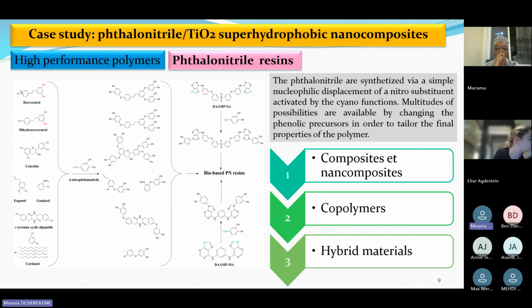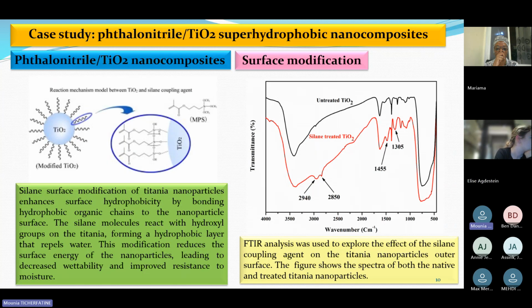Prior to the nanocomposites preparation, a chemical surface modification is applied to the titania nanoparticles to improve their adhesion and dispersion within the polymer. The silane surface modification of titania nanoparticles also enhances surface hydrophobicity by bonding hydrophobic organic chains to the nanoparticle surface. The silane molecules react with hydroxyl groups on the titania, forming a hydrophobic layer that repels water. This modification reduces the surface energy of the nanoparticles, leading to decreased wettability and improved resistance to moisture.